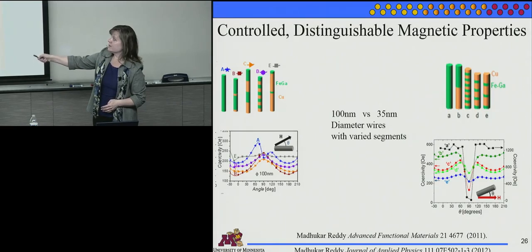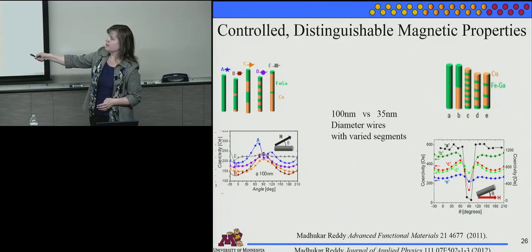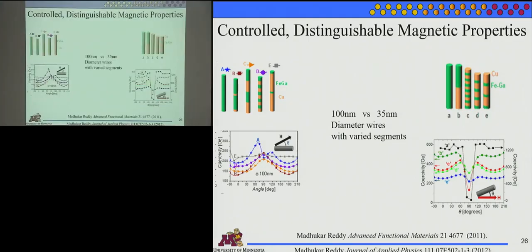And E, what's different about E? You can see all these properties are changing, but E is the extreme one. Well, in the case of E, they're all sort of isotropic, and they're separated from each other by a lot of copper. They just don't really see each other. So these are more like isolated nanoparticles. But for those of you in bio, they're like nanoparticles that are already nice in a chain. So you can see the signal that they're giving, which is convenient for a lot of applications.